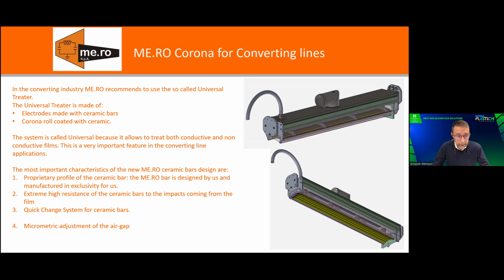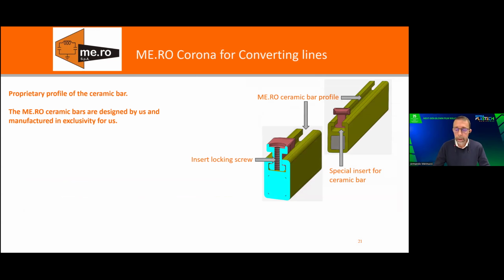And last but not least, the possibility to adjust the gap in a very fine way. We can see from this slide the profile that I told you before. This is a Mero design. We have a special channel on top of the profile where we put some aluminum inserts that link the ceramic bar to the main structure, to the main support. This is a specific design. It's only Mero that has this design.